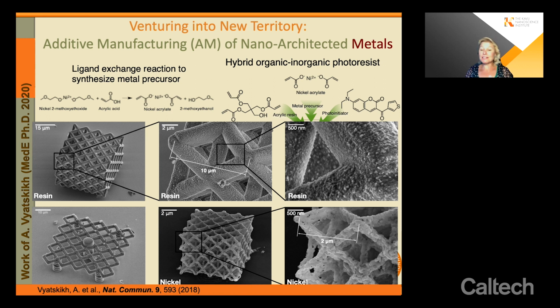Now, using this process called pyrolysis, which is a fancy term for burning in the absence of oxygen, Andrei was able to volatilize all this organic content and to be left with fully nickel nano-architected materials whose dimensions are much, much smaller. So this process of pyrolysis certainly reduces the dimensions and shrinks everything that we make. You can see, for example, the beam diameter here is on the order of 400 nanometers, and the overall unit cell shrunk from 10 microns down to 2 microns.